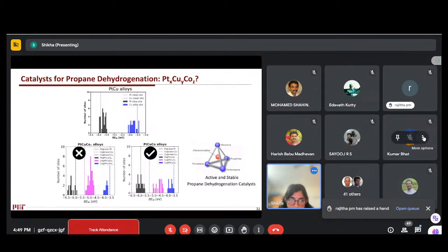When we add cobalt in a very large amount, then we lose the activity of the site. It makes the system more stable, and the sites become more stable, which we do not want. When we have all three atoms in the same ratio, then the activity is reasonable for our platinum sites, and the stability is also good at the high temperature at which they perform the reaction. So we can see where our spectrum is lying and how much statistics we have on our active sites and on our less active sites. That way we can answer the question from our model, and we also predicted more alloy surfaces for other chemical reactions as well.